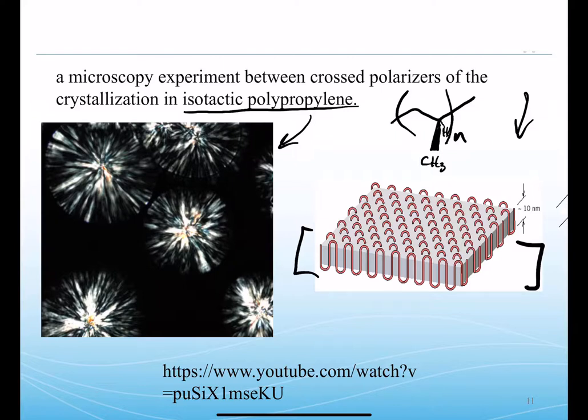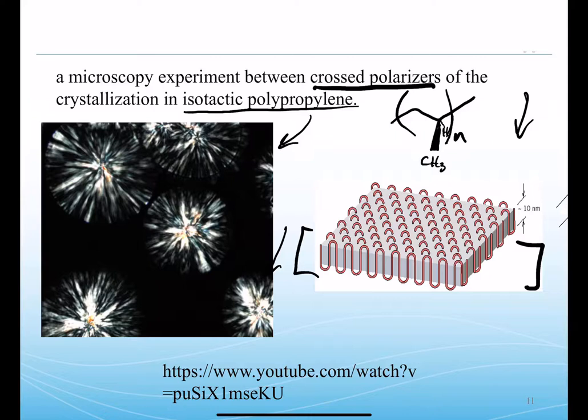The crossed polarizers use the crystals as an optical filtering element to allow light that would otherwise not make it between crossed polarizing filters to pass through. The crystals interact with the light to twist plane polarized light, allowing it to pass through an optical filter that would otherwise block it. These crystals can twist plane polarized light, allowing them to shine bright and give us features on the micrograph. These fibrils emanating from a central feature represent lamellae that we need to understand in three dimensions.